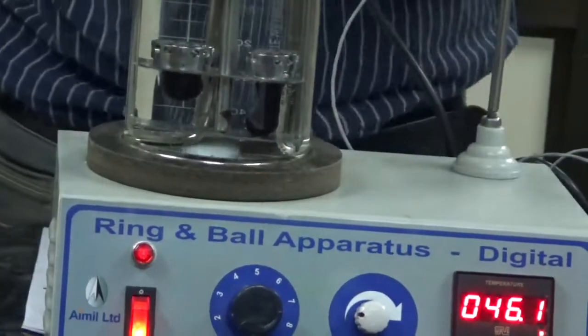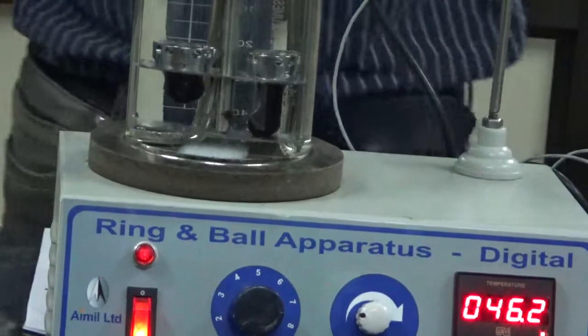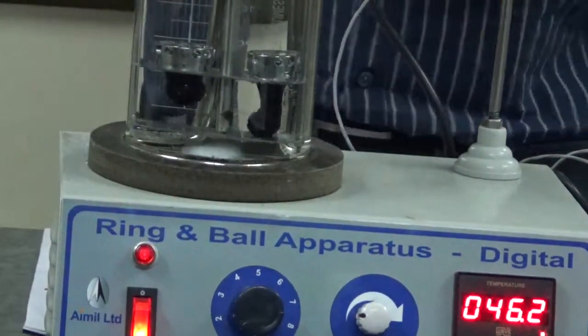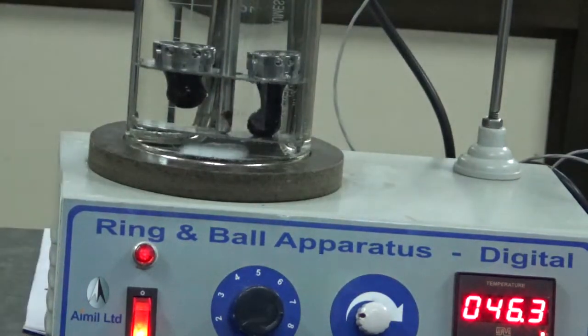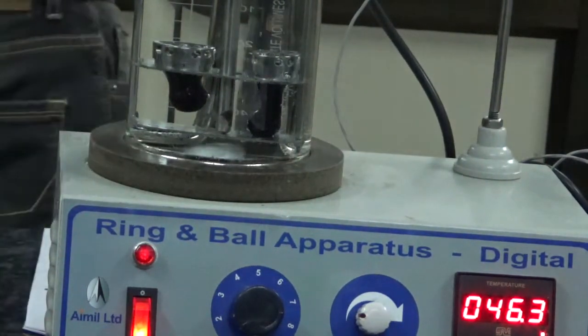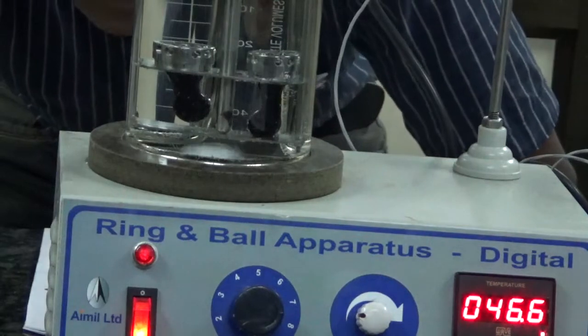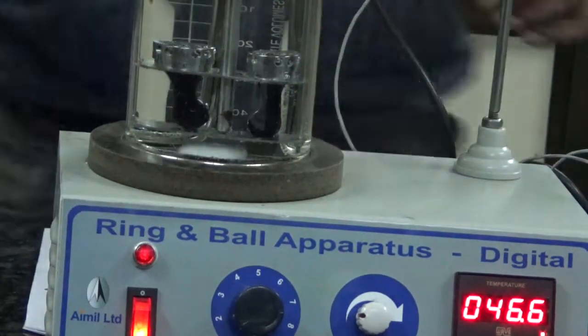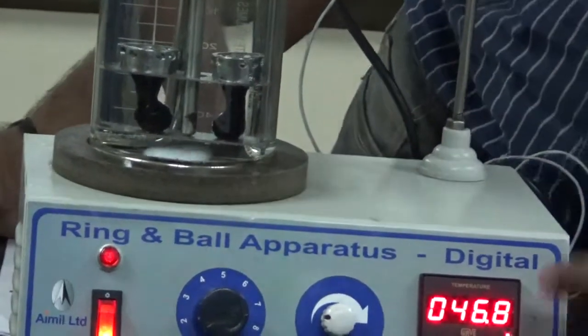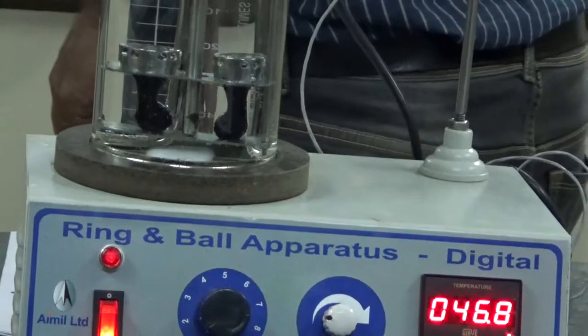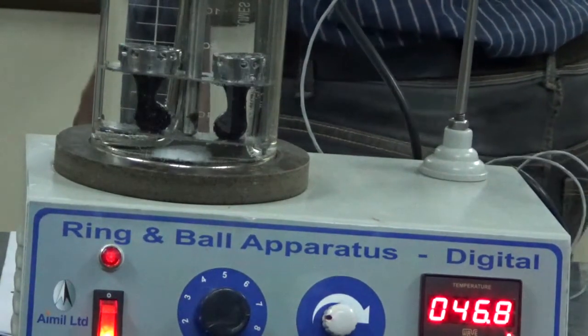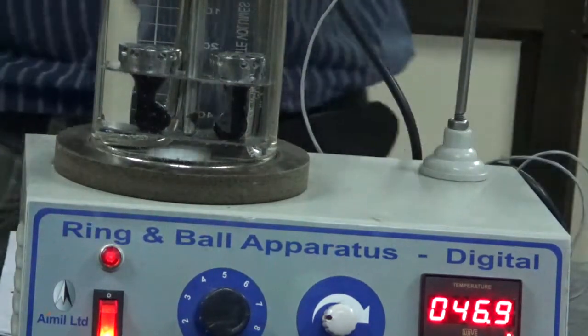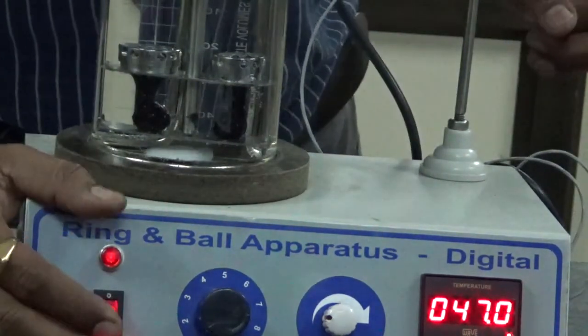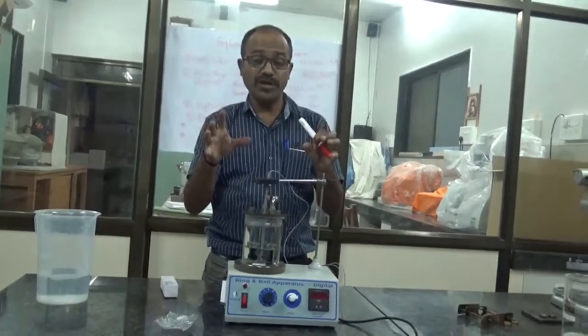Okay, the first ball is touched, at 46. The temperature was 46 degree centigrade, so just write down 46 degree centigrade. Let us wait for the second. The second ball also is touched, and it was 46.6. So the average softening point, we can say, I am going to stop this test. My softening point has been reached. The average softening point is 46.3.